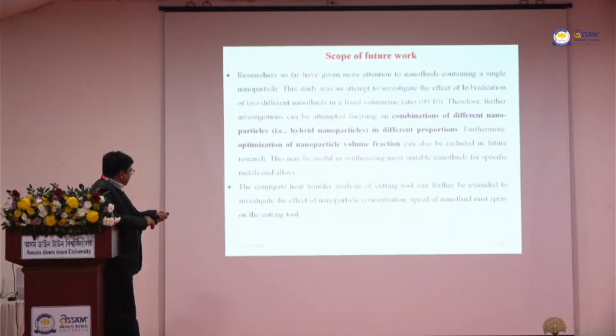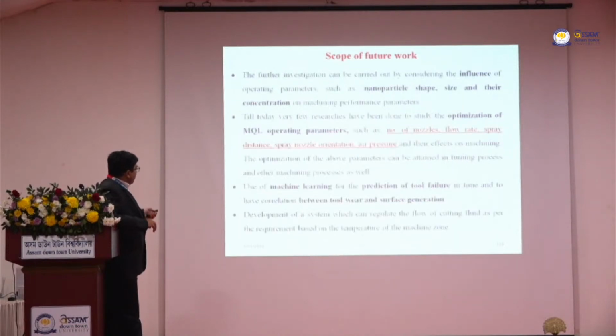Next, the conjugate heat transfer analysis I also did, but did not explain here. So that can also be attempted. But the important thing is, in the minimum quantity lubrication technique, we used a single nozzle for the MQL system. So the number of nozzles can be attempted. Flow rate of the cutting fluid spray can be varied, and it can be investigated. Spray distance can be investigated, spray nozzle orientation, air pressure. So there are other parameters also which can be investigated. Also, I have taken the spherical shape of alumina and other particles, but different shapes can also be investigated. Use of machine learning for the prediction of tool failure. So many people are doing this work also, but still it is not saturated. So it can also be tried.